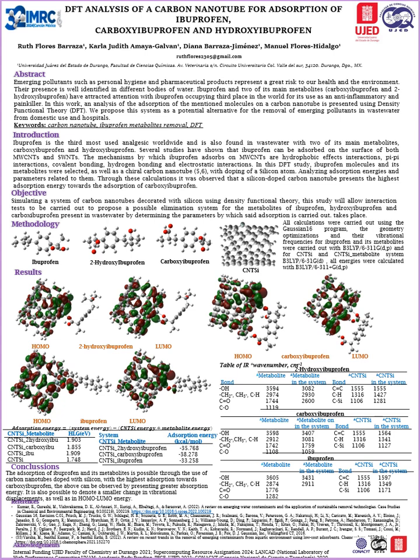The adsorption of ibuprofen and its metabolites is possible through the use of silicon-doped carbon nanotubes, with the highest adsorption towards carboxyibuprofen. This can be observed to represent greater adsorption energy. It is also possible to denote a smaller change in vibrational displacements as well as in HOMO-LUMO energy.